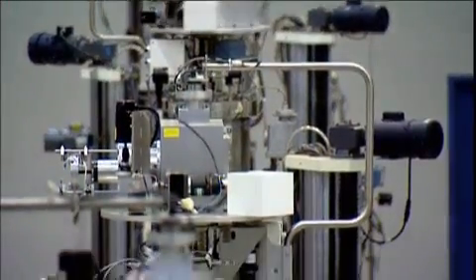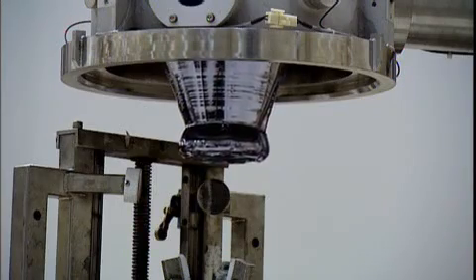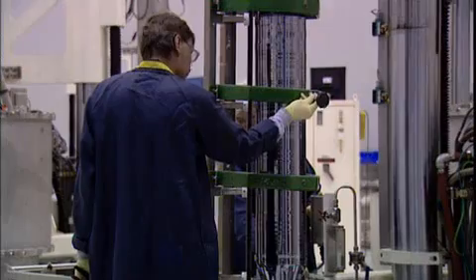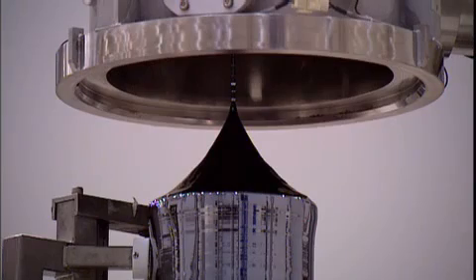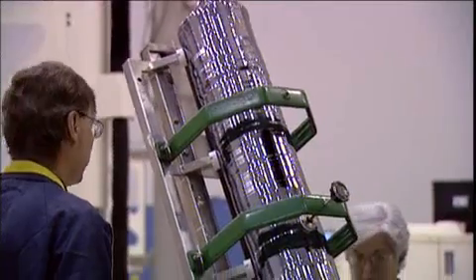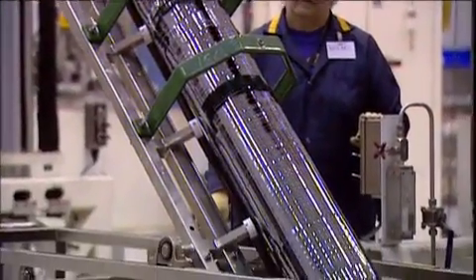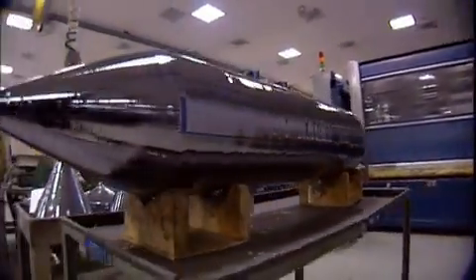The result is a single silicon crystal weighing around 200 kilos and with a diameter of around 200 millimeters. The crystal is so strong, its entire weight can be supported by a single thread just 3 millimeters across. But it is brittle, and it must now be cut down to size without shattering. So, after testing with chemicals and X-rays to check its purity and molecular orientation, it's fed to a silicon salami slicer.